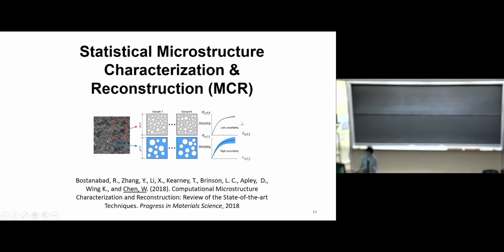If you choose a very large window size, for a linear behavior, there's almost no uncertainty. For plastic behavior, you see a little bit of uncertainty. But for some other very nonlinear behavior, like buckling and some other plasticity behavior, you can see that the window size has a huge impact. Using the SVE, this is called SVE, is oftentimes due to the lack of computing power. So in order to account for the uncertainty, we had to do multiple realizations so that we can look at the impact of the lack of computing power. That's the reason we created this method called reconstruction, to try to reproduce statistically equivalent microstructures so that we can see their impact on the property uncertainty.